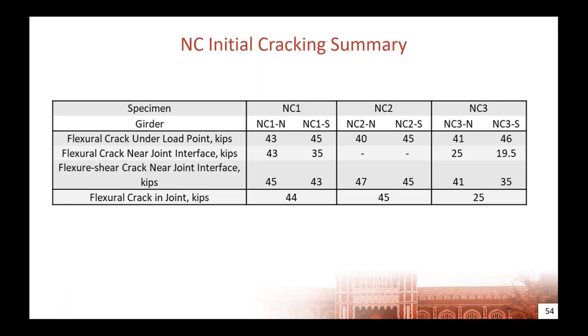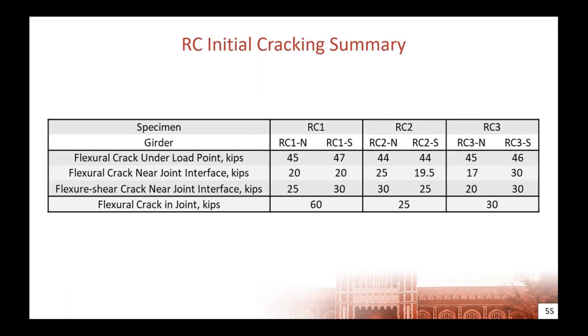And we saw that crack happen earlier in that third specimen that was tested for positive moment first. For the retrofit construction specimens, we saw the first crack under the point load at a little bit higher load, so a little stiffer specimen. We saw the first cracks near the joints, however, at lower loads than what we saw for the new construction.